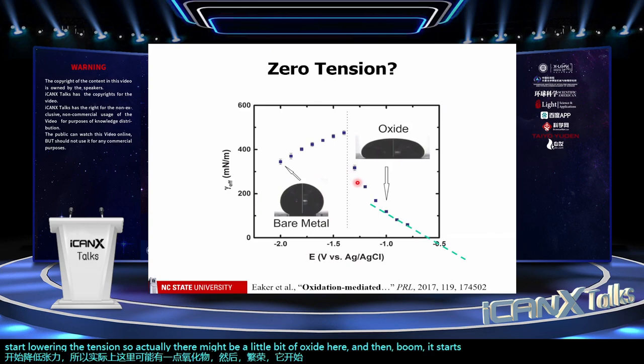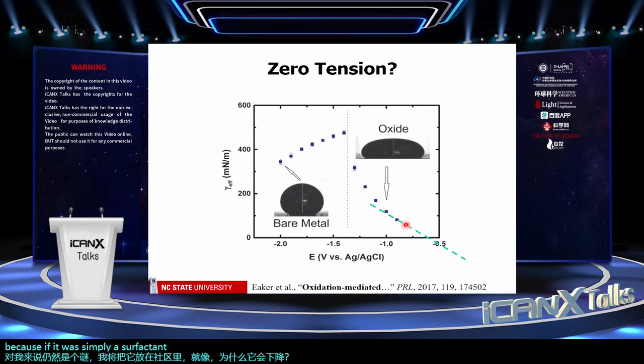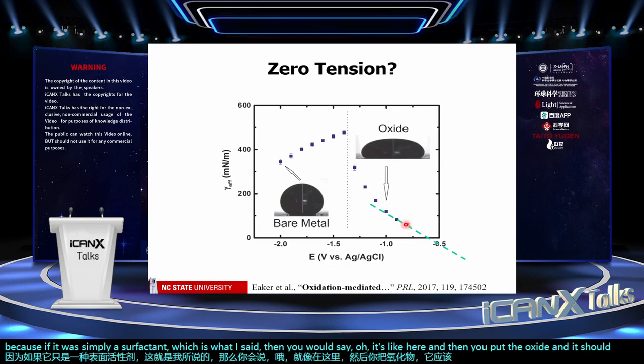And the thing that is still a mystery to me, which I will put out there for the community, is why is it dropping? Because if it was simply a surfactant, which is what I said, then you would say, oh, it's like here, and then you put the oxide and it should drop, and then that's it. It should just be bistable. It shouldn't be a continuous drop.